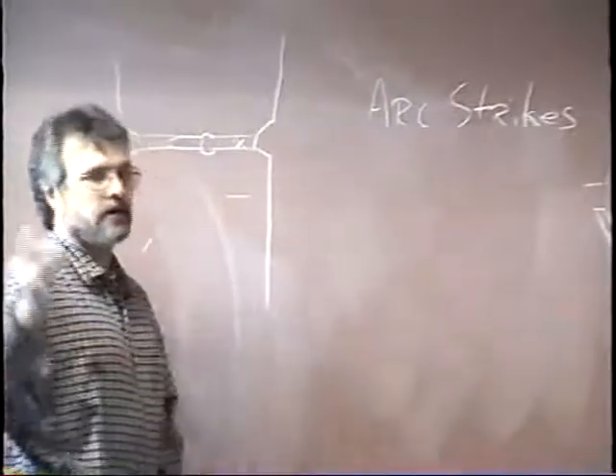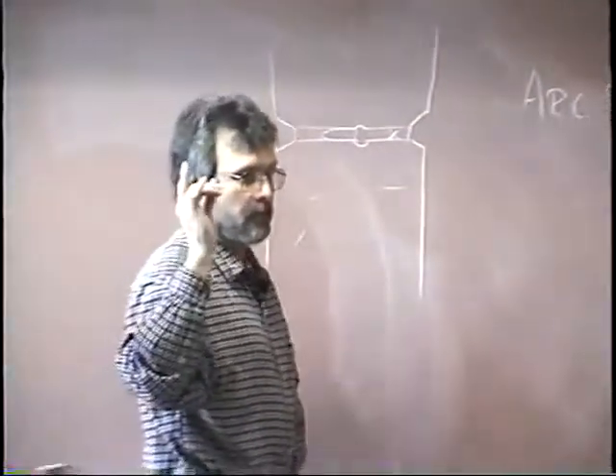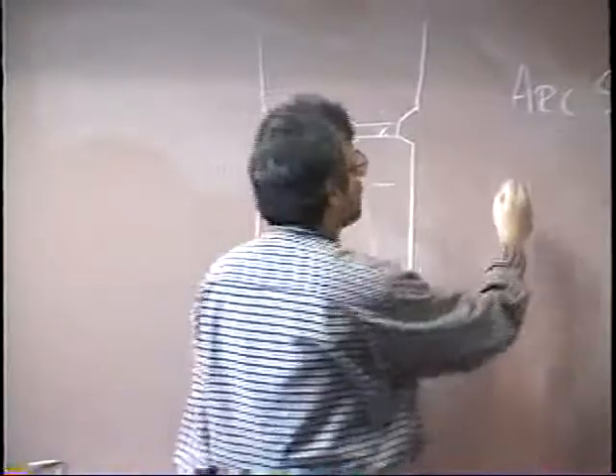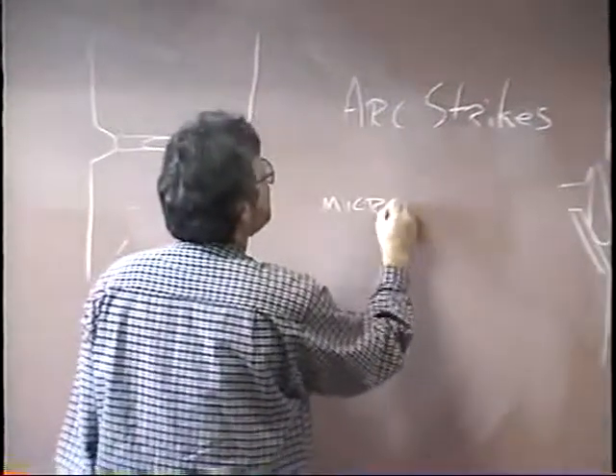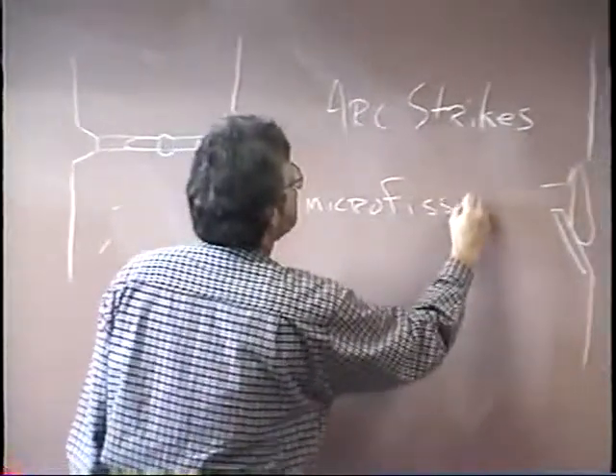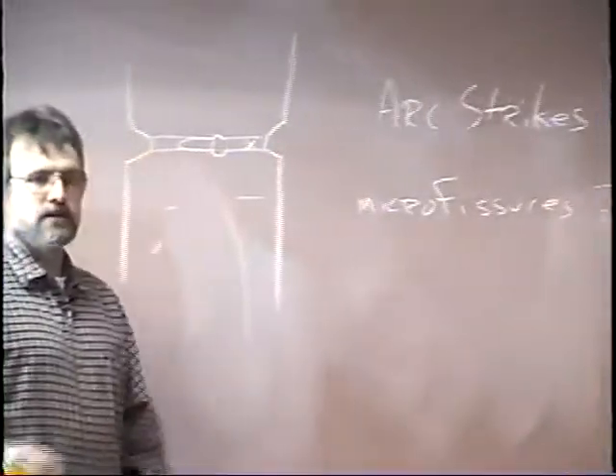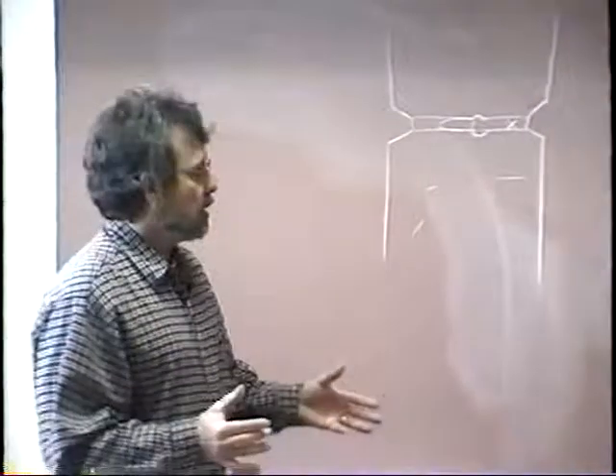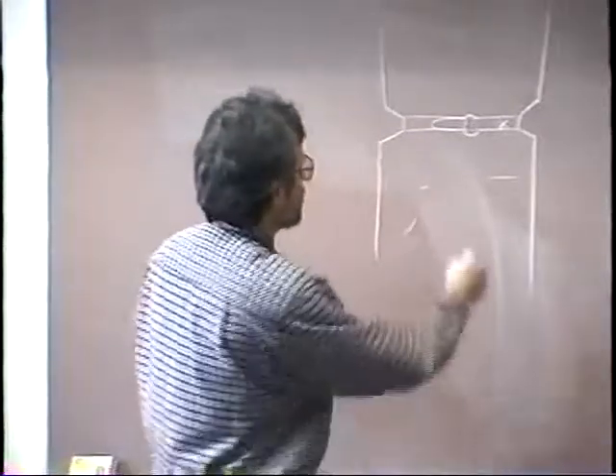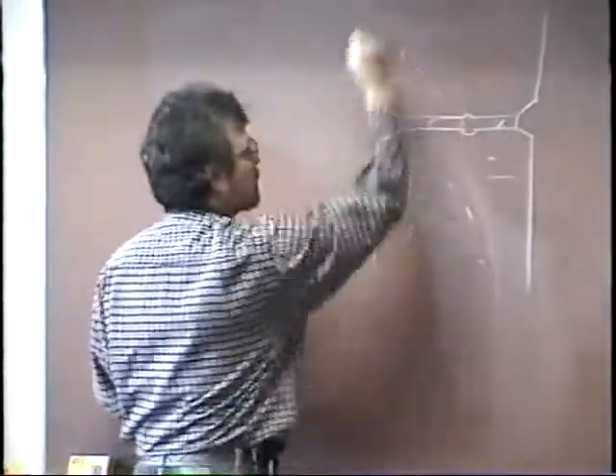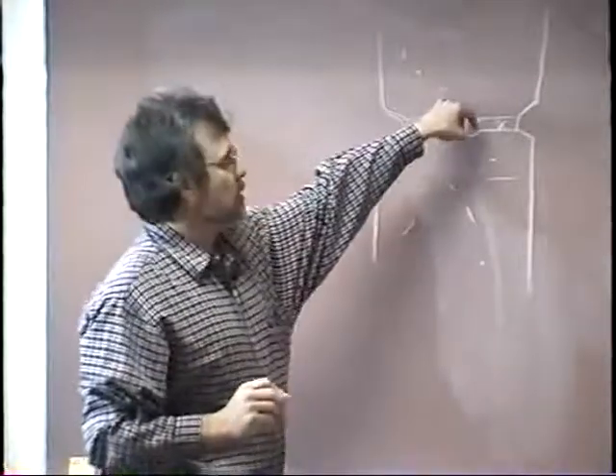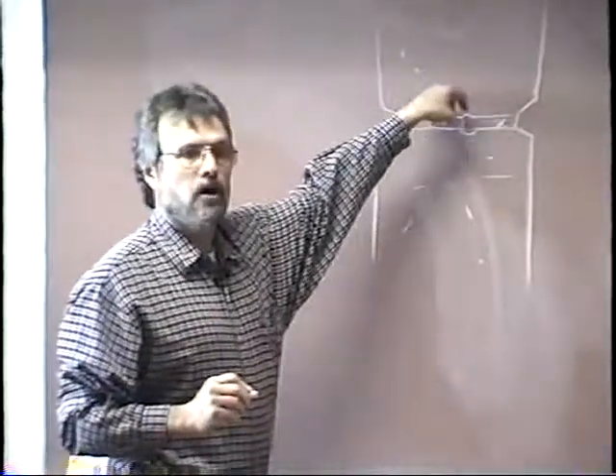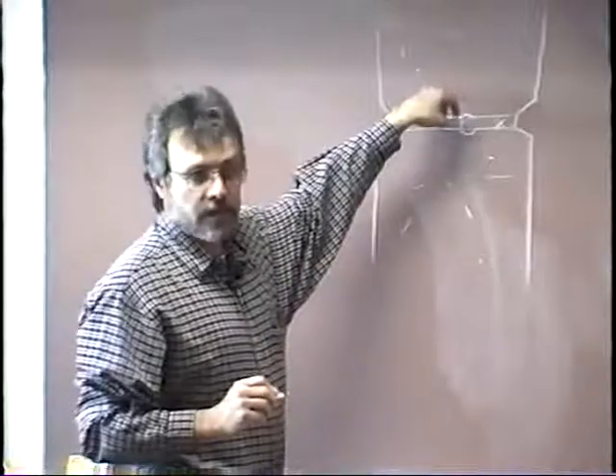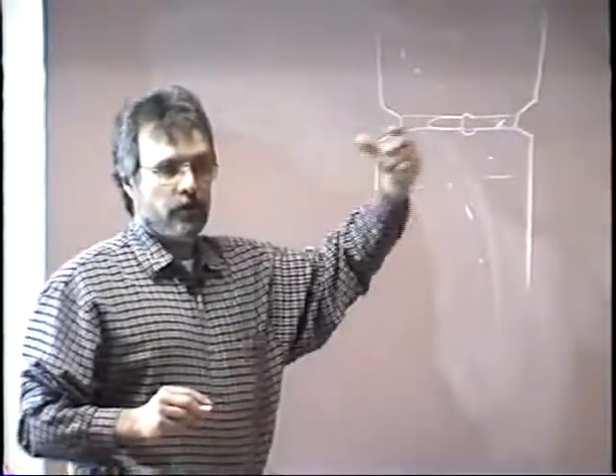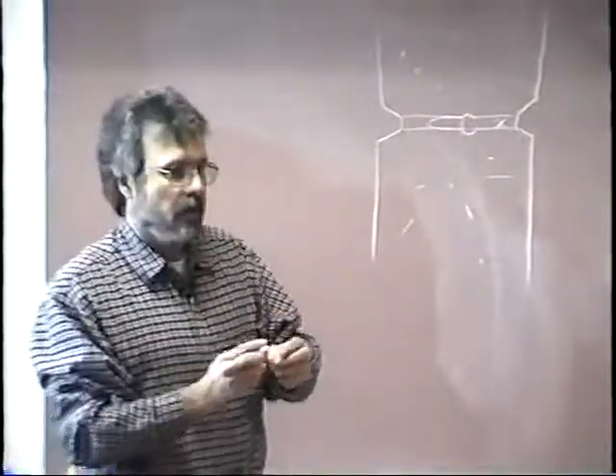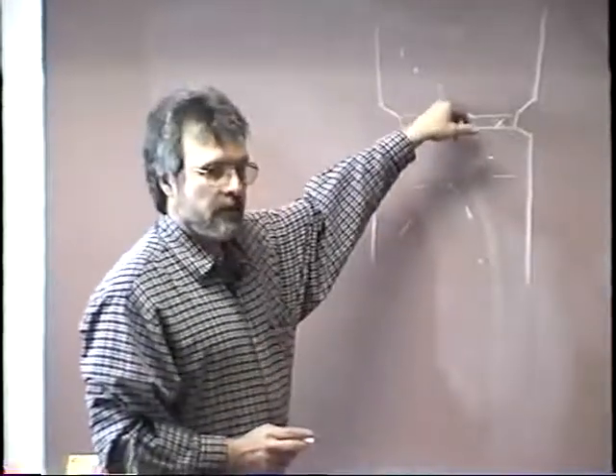And what's the danger of arc strikes? Weakens the joint or weakens the metal. It does weaken the metal through what they call micro fissures. Little tiny cracks that you can't hardly see with the naked eye, but every time your arc strikes the surface of that steel, you're changing the physical properties of that steel and causing what's called a martensite structure, which is highly abrasion resistant, but it's hardened, and so it can cause cracking in here.